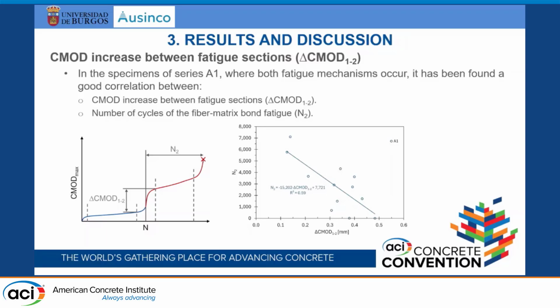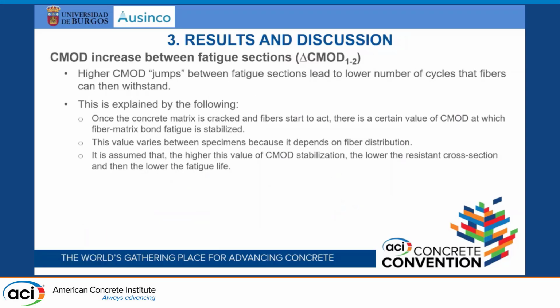So what does that indicate? What is the physical explanation for that? Once the concrete matrix is cracked, there is a certain point at which the fiber-matrix bond fatigue is stabilized. This value changes because it depends on the fiber distribution. So in some specimens the jump is lower, in others it is higher. As this CMOD is higher, that means that the real section that is supporting the specimen is lower, and therefore the fatigue life becomes also lower. So that could be the explanation.